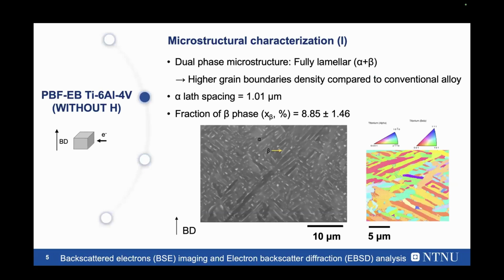So to start with, as mentioned, it's a dual phase microstructure, which is fully lamellar as shown in the SEM image. It's backscattered. And you can see that the darker gray phase is the alpha phase, and the white phase is the beta phase. And we can also see that the grain size is significantly lower compared to conventional alloys, which also leads to higher grain boundary density that is also going to have an effect on the hydrogen embrittlement.